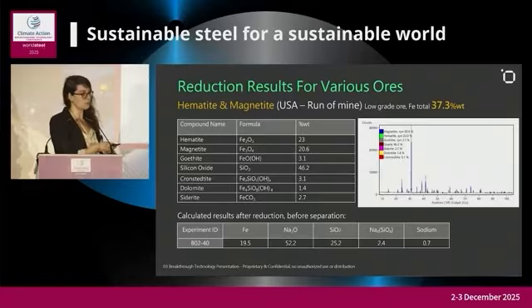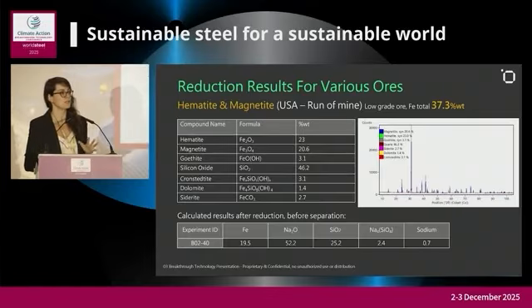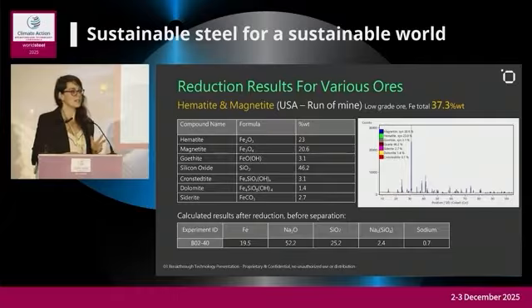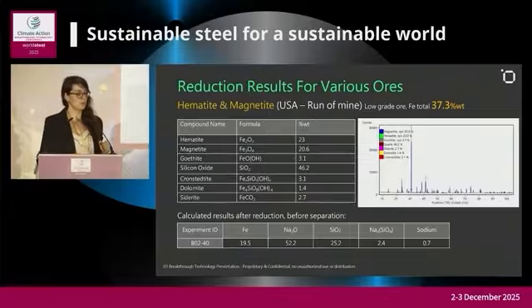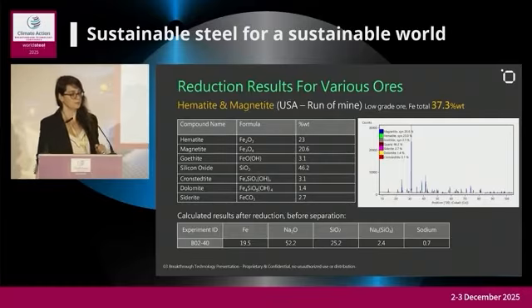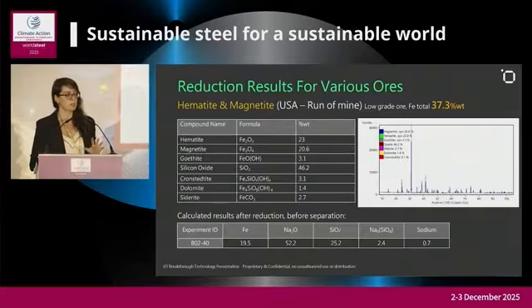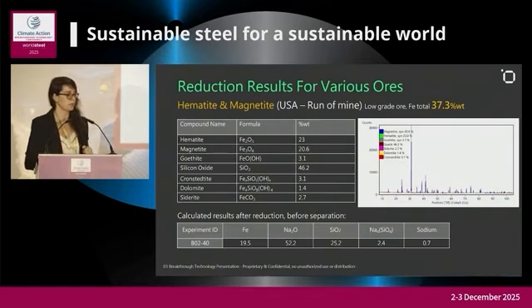So let's move on to the first example. We've conducted hundreds of experiments with different types of ores, and I will demonstrate 3 of them. One is a low-grade ore, unbeneficiated, with an Fe total amount of 37.3%. It contains hematite and magnetite, and you can see in the XRD analysis that this is the composition. In the table below, you can see the results after the reduction, before the separation steps. I will explain later what the separation steps are, but this is only the result of the reduction itself, meaning most of the iron oxide turned into metallic iron, and sodium oxide, of course, as a consequence of the reduction.